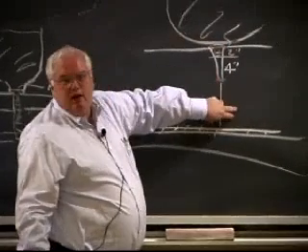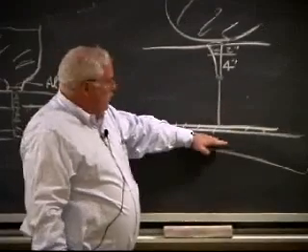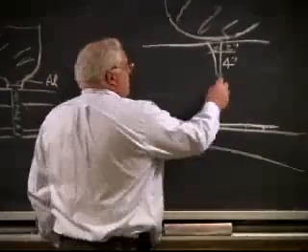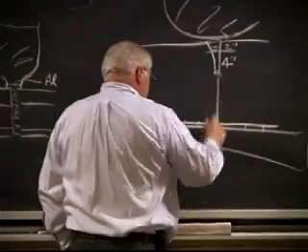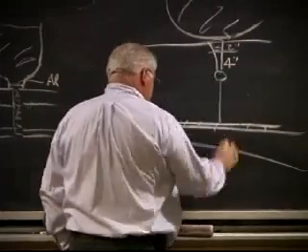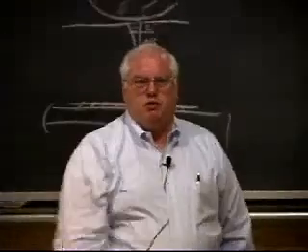The stresses down here are like 10 or 20 KSI, even without a joint. And we can support that by just a 2-inch plate, fillet welded on the bottom. The problem is you're going to have defects here, so what do we do? We make the weld, and when we're all done, we drill, I think it's a 3/4 inch hole. We just drill out the root, 30 inches deep.